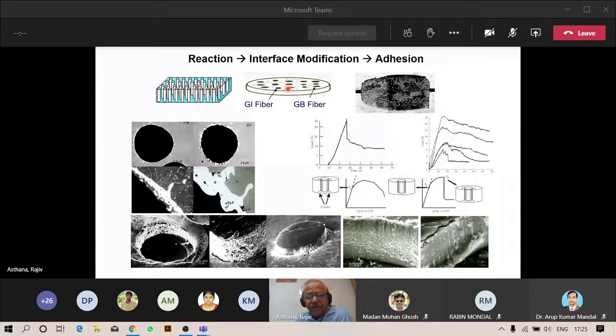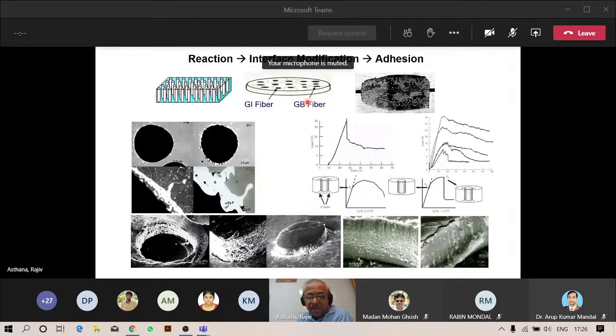So what we did was we sectioned small wafers of the composite after directional solidification, did microscopy and all that, and we tested the bond strength of the fibers that were confined within the grain and the fibers that were sitting at grain boundaries. And we did fiber push-out tests, a lot of these kinds of fibers, and some of you might be familiar with that. It's the precursor to the more recent nano-indentation kind of test. But you essentially slide the fiber out of a thin wafer and record the load versus time or stress strain plot. So what we found was that fibers that were completely engulfed within the grain had much higher bond strength than the fibers that were sitting at a few grain boundaries.